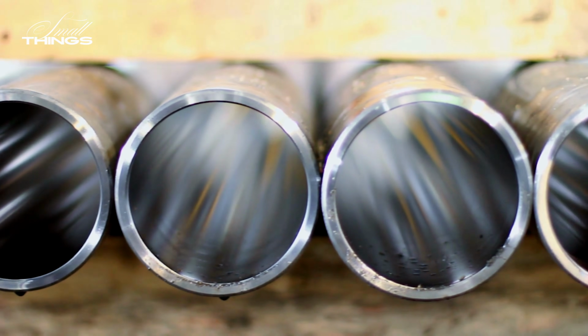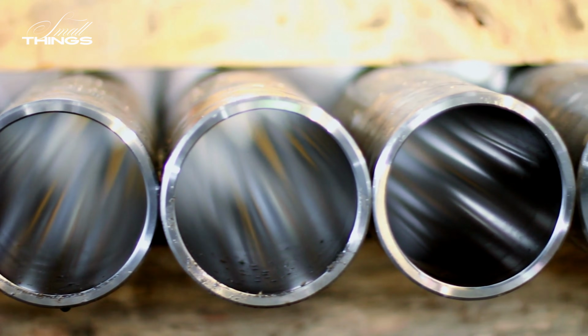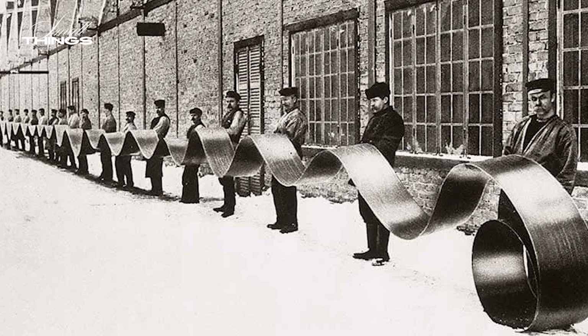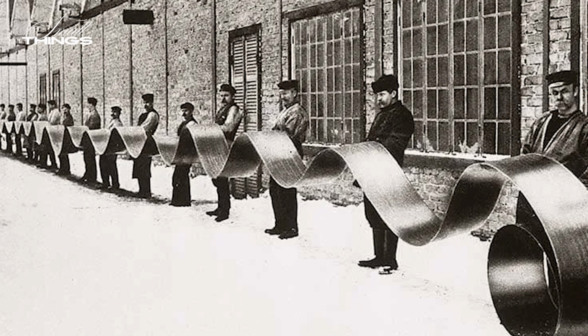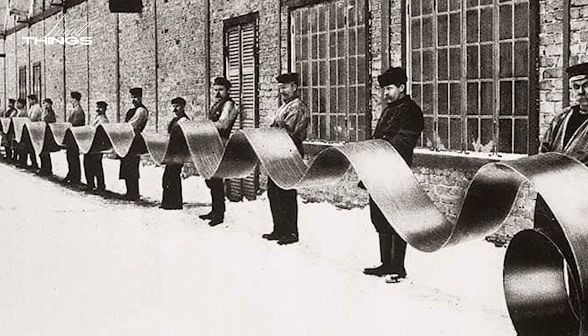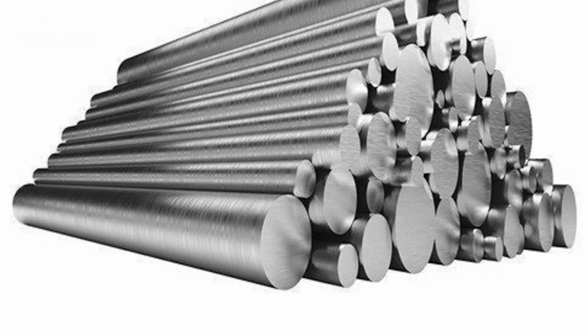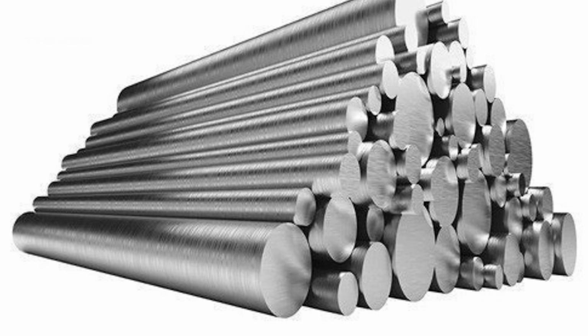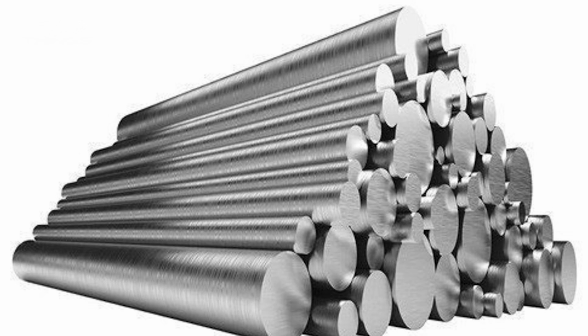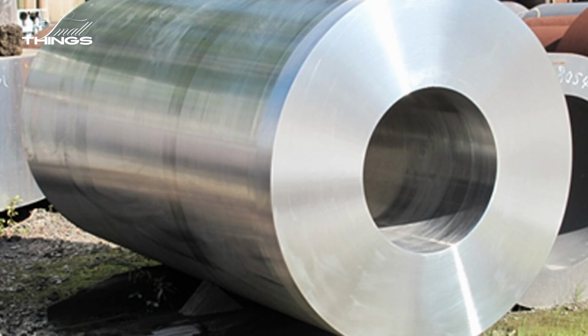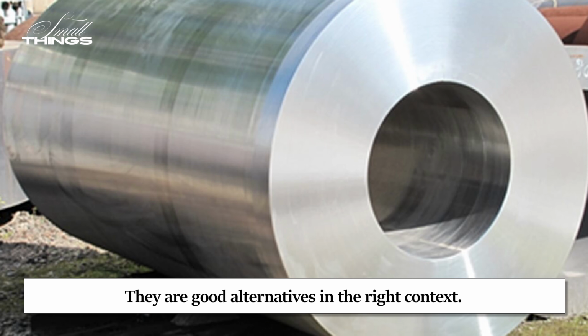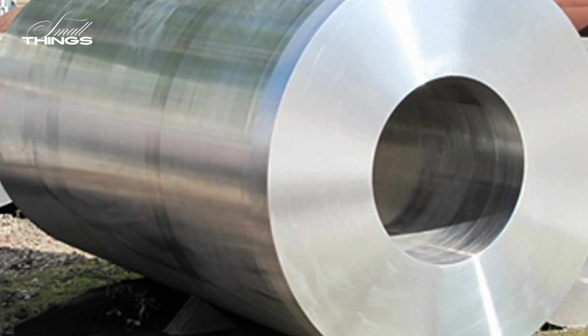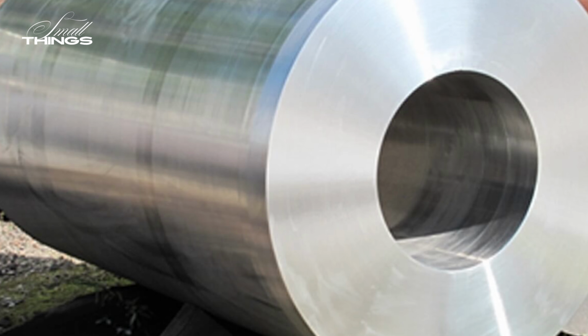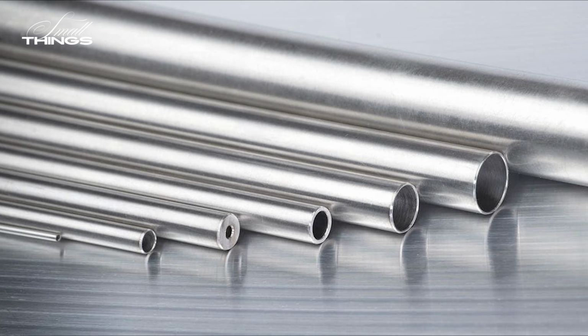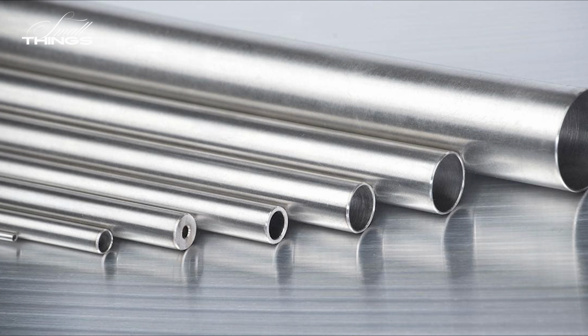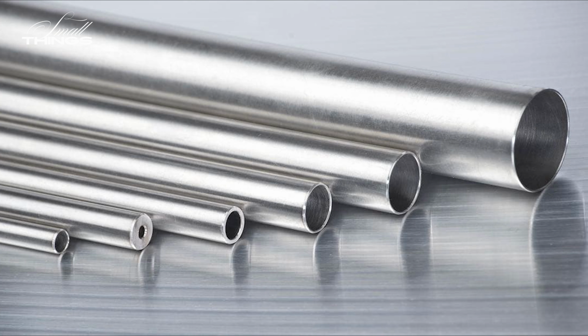Several alternatives have been developed and are used successfully in certain marine environments. Super duplex stainless steels offer excellent resistance to stress corrosion cracking and are strong enough for structural marine applications. An alloy called Al6XN was developed specifically to combat seawater corrosion and performs well in desalination and power plant contexts. These are not inferior materials, they are good alternatives in the right context. But super duplex steels are more difficult to weld than Monel, and in certain acidic environments, particularly those involving reducing acids rather than oxidizing ones, they do not match its resistance.